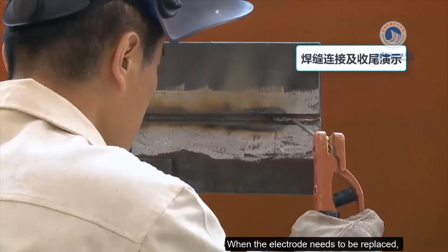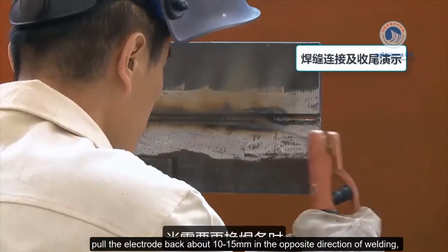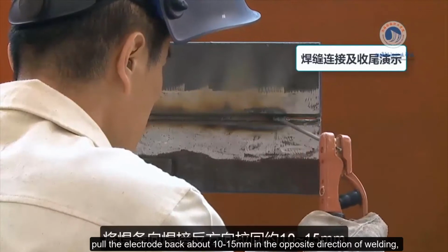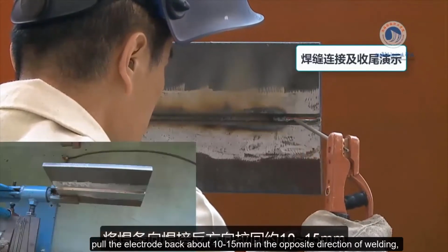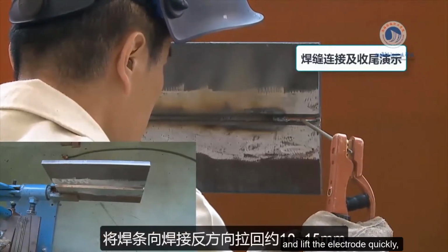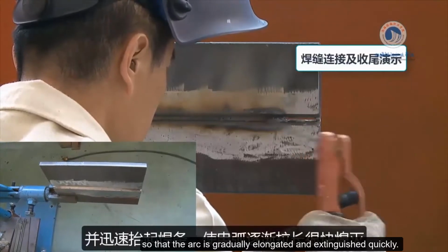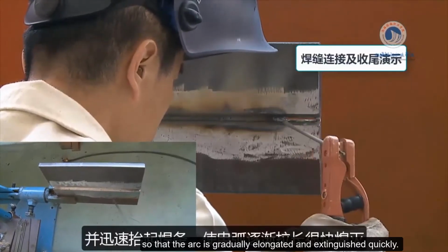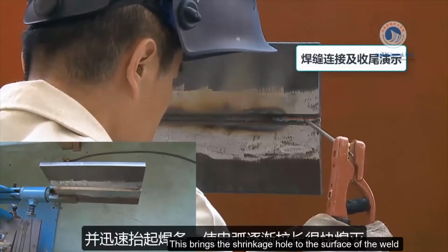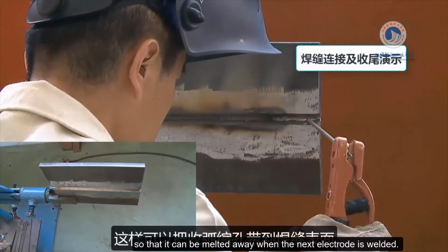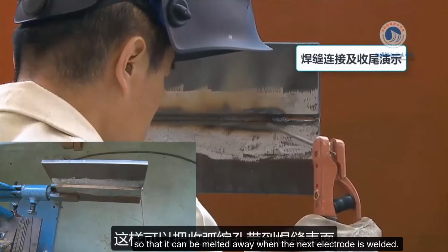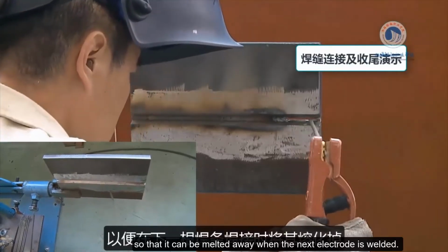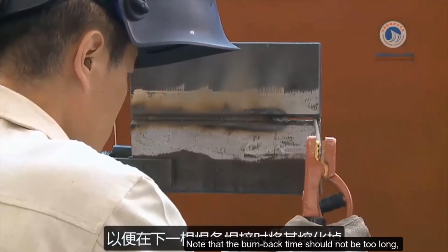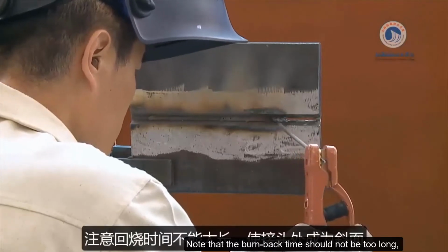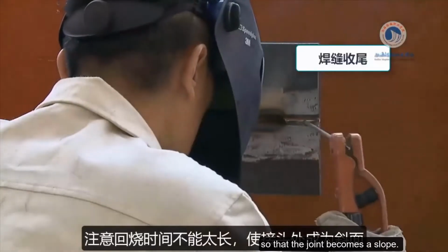When the electrode needs to be replaced, pull the electrode back about 10 to 15 mm in the opposite direction of welding, and lift the electrode quickly, so that the arc is gradually elongated and extinguished quickly. This brings the shrinkage hole to the surface of the weld so that it can be melted away when the next electrode is welded. Note that the burn-back time should not be too long, so that the joint becomes a slope.